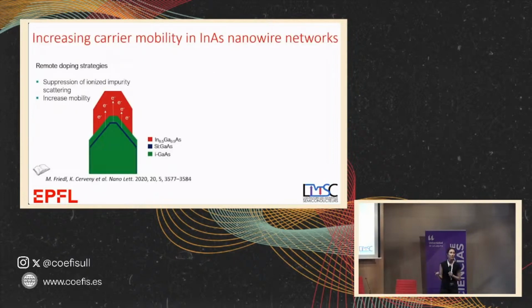Now these wires, if we don't do anything, they don't conduct. As we saw in the last talk, semiconductors, you dope them by putting, in silicon, you add phosphorus or boron, and it has one electron more or one electron less. So you need to dope them. When you do this, you change the mobility, and then you increase the collision. So it doesn't work.